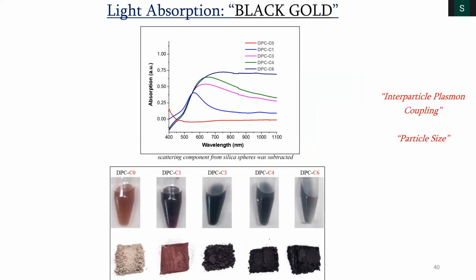So you can see now the light absorption behavior. When you only have gold nanoparticles supported on silica, they are like this. They are brown or light red in color. But with more and more cycles, that means when I bring the gold particles nearer and nearer, you start seeing a black gold, physically a black gold, a material which is gold but black.